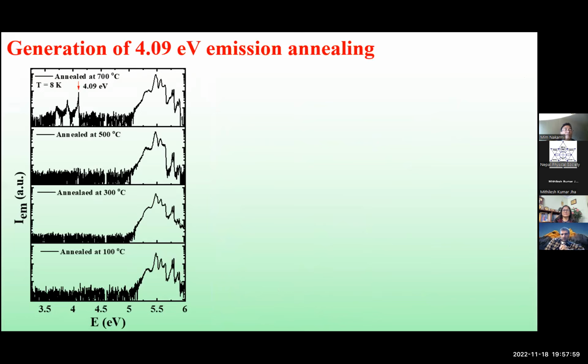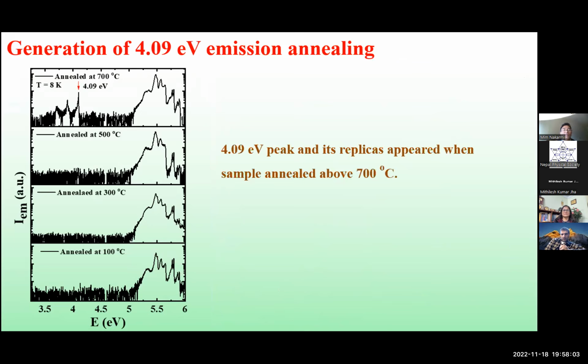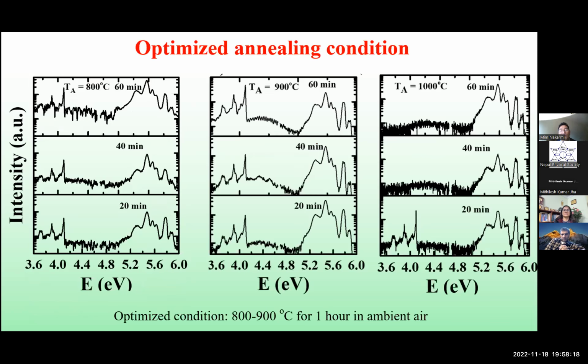emission line. We annealed at different temperatures, keeping the same time, and most of the time we see that sharp emission at 4.09 after annealing above 700 degrees C. We further tried to figure out the optimized temperature and time. If the temperature is too high, let's say 1000 C, it doesn't give that emission. If it is low temperature, we have to anneal for a longer time. The optimized condition is 800 to 900 degrees C for 1 hour in ambient air.